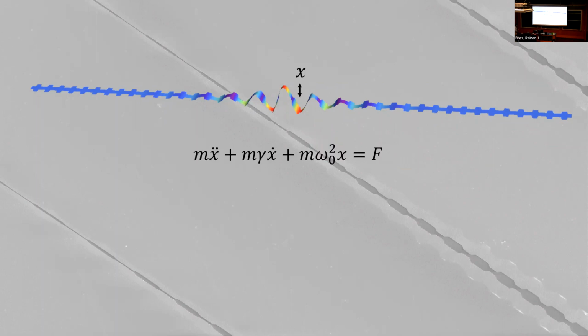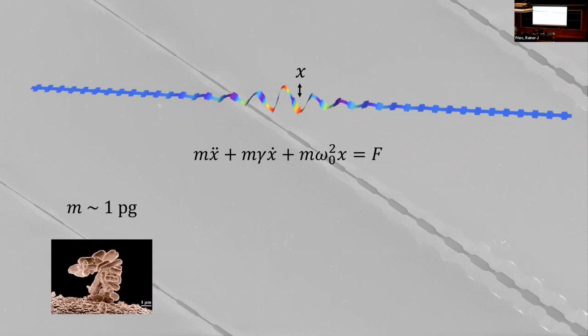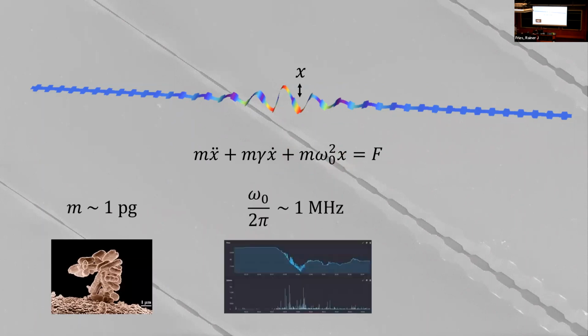So we can think of the transverse vibrations of this beam as a simple harmonic oscillator. It's actually a fairly good model. We could just think of it as described by the equation of motion for a damped harmonic oscillator. But because of the dimensions of this device and the high material stress, the actual mass, damping rate, and frequency of this oscillator are a little bit peculiar. So this is really only 100 microns long and 10 nanometers thick. So the effective mass of this little vibrational mode is around a picogram, which is like the mass of an E. coli bacterium. The frequency is around a megahertz. It's pretty high because of the high stiffness of the material and the small dimensions.